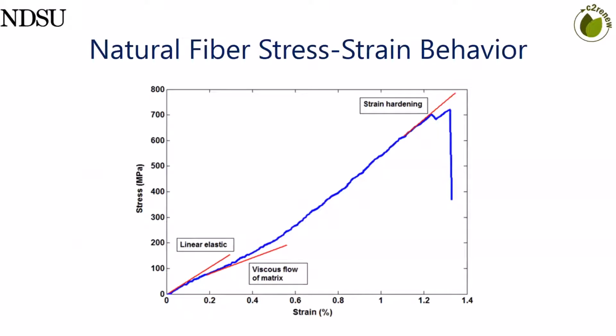In some of the study that we've done on natural fiber stress-strain behavior, we've tested thousands of single fibers, and one type of behavior that a majority of the fibers we've tested from flax and hemp show is this triphasic stress-strain behavior. I won't get into many details, but we have an initial linear elastic behavior followed by some non-linear viscous flow. And then after a bit of time, we get this strain hardening effect where the alignment of those cellulose chains takes place until the ultimate rupture of that particular fiber.